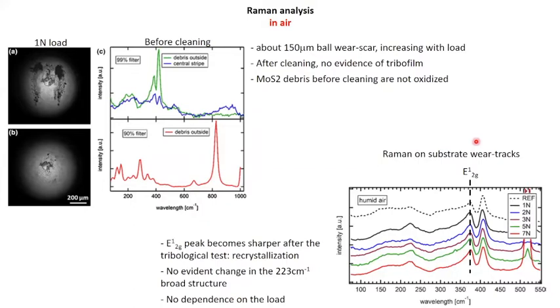With Raman analysis, we also analyzed the crystallographic order of the coating, increasing the load. So we repeated the experiments at 1 Newton, 2 Newton, 3 Newton, 5 Newton, and 7 Newton. And again, we look at the shape of the peak here at 375. And again, we found a recrystallization of the material related to the sharpening of this peak, but we did not find any dependence of the recrystallization on the load.